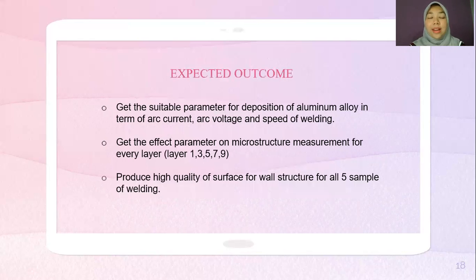My expected outcome is to get the suitable parameter for deposition of aluminum alloy in terms of arc current, arc voltage, and speed of welding. Get the effect of parameters on microstructure measurement for every layer, which is layer 1, layer 3, layer 5, layer 7, and layer 9, and produce high quality of surface for wall structure for all 5 samples of welding.